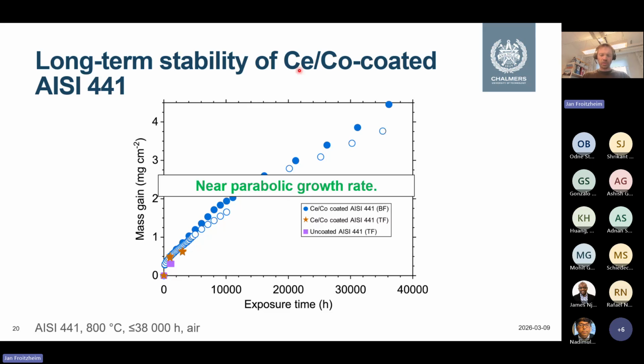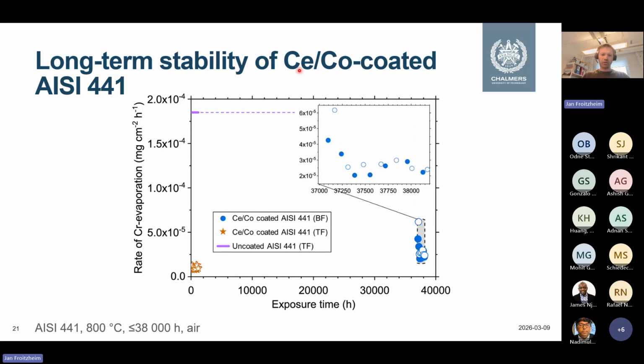But in terms of chrome evaporation, we couldn't measure for 40,000 hours, and we didn't want to. So instead, we measured initially those data you had seen before, then took those samples after 38,000 hours and put them back into our setup and measured again. Initially they're higher, but it drops within maybe 200 hours or so, and we know what is happening there, then it basically goes back to the same values we had initially. So even for these very long exposure durations, the coating performs very stably.